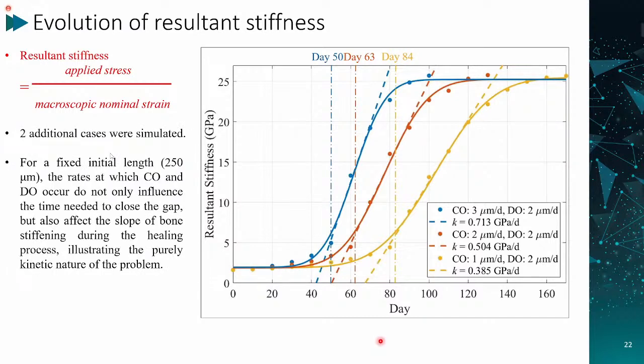We also calculate two additional cases, which means we have different kinetics. So the blue curve is the CO faster than the DO. And the red curve means the CO and DO have the same rate. But for the yellow curve, which means CO progresses slower than the DO. So three different kinetics. We can see for a fixed initial length, which means 250 micrometer in this model, the rates at which CO and DO occur do not only influence the time needed to close the gap.